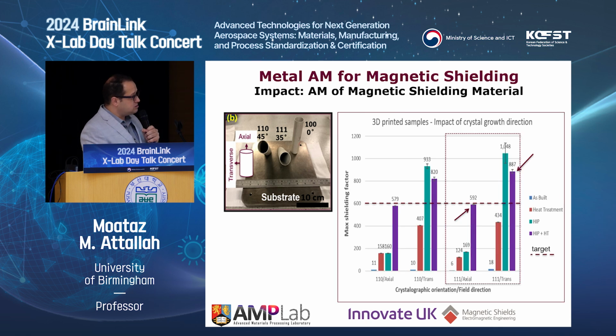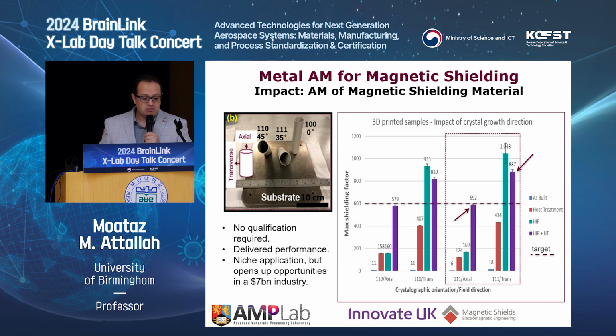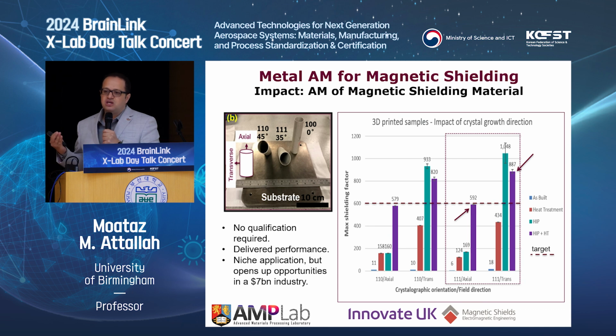And as a result, the parts we printed, when we talk about their shielding efficacy, if we compare it to the standard material, we are way above the standard material. We're getting very high shielding capability from the material, even more than the target. Of course, with some heat treatment, with some hipping to get into that right performance. But in a way, that reached the point that we are actually happy to deliver. It's basically no qualification required beyond the ability to deliver the magnetic performance, which it can deliver.